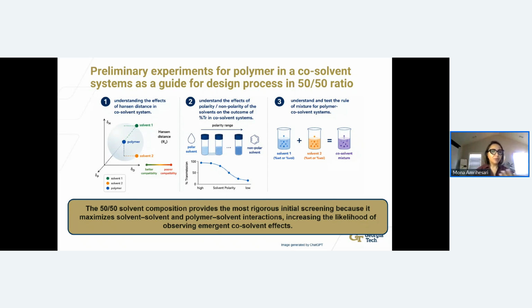Then we started preliminary experiments. We looked at the effect of the Hansen distance in the co-solvent system. We have one polymer, solvent A and solvent B. The Hansen distance is different based on different parameters. So we looked at the Hansen distance between polymer and solvent A and solvent B. We wanted to understand the polarity of the solvents and the effect of the polarity on the phase separation of the polymer and the effect on the transmissivity results in the co-solvent system. So we looked at that.